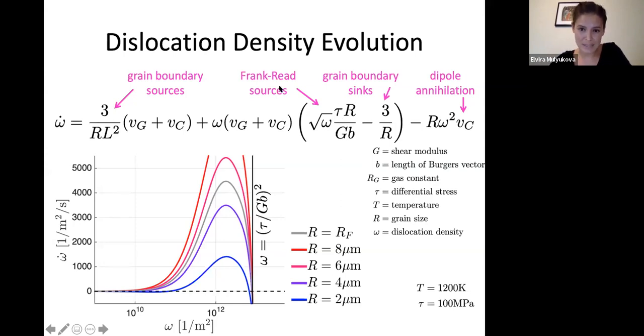Here again, the efficiency of the source scales with stress and with grain size, because the maximum distance between the pinning points of a dislocation that you can have within a crystal is limited by the size of the grain. So you can't have a dislocation that will bow out that is longer than the size of the grain. And it depends on the dislocation density as well, just because you need the presence of other dislocations that may act, for example, like pinning points that would hold it in place as it bows out.